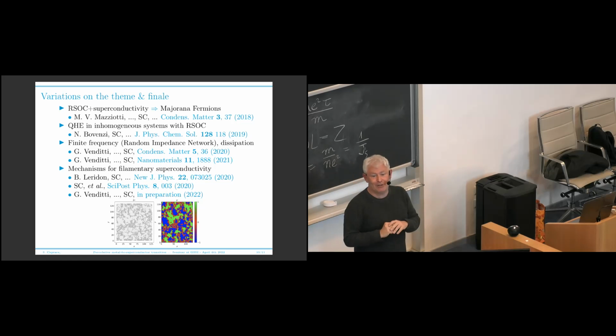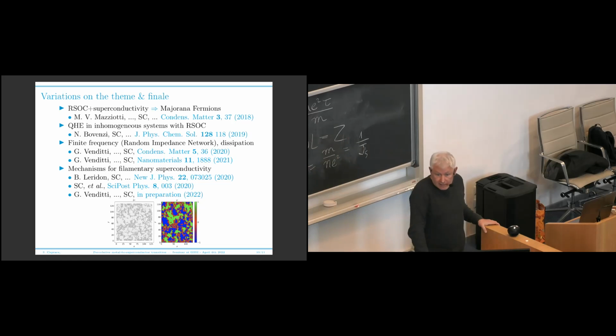Now put some disorder in your system. In this effective model, disorder is a random field. Because of the random field, you will create some domains where you prefer charge density wave up and other domains where you prefer charge density wave down. Now, if you want to go from one domain to the other, you must go through a region where your spin is in the XY plane. And to our surprise, if you measure the superfluid stiffness of this system, it is finite and even larger than TC, than the temperature, in most cases. So you have real superconductivity in the system. So this is what we found.